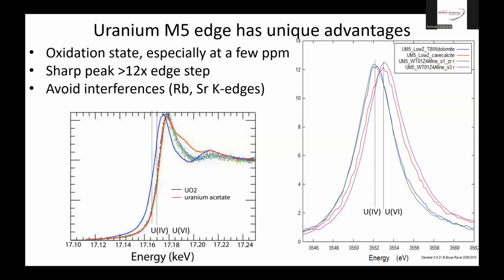That issue with potassium. It's below the potassium edge, so. Oh, I was looking at M4. Right. Yeah, the M4 hits potassium, but the M5 edge of uranium is below the potassium and calcium edges. So two commonly very abundant elements, so you're nicely not activating them. So you're staying away from interferences pretty well.